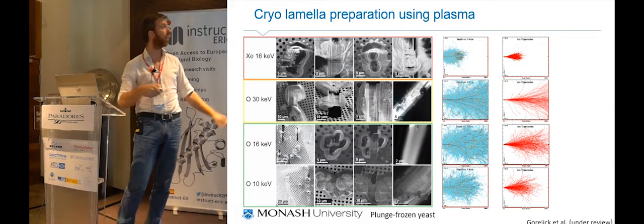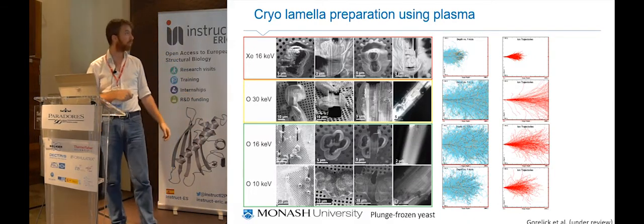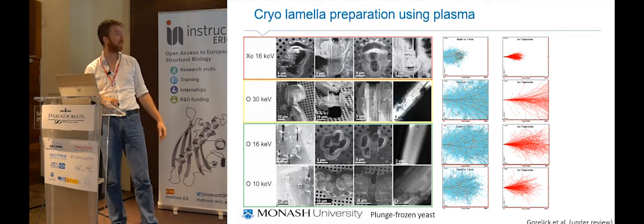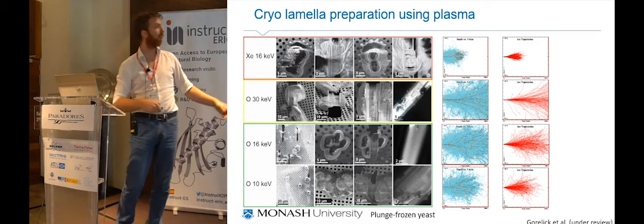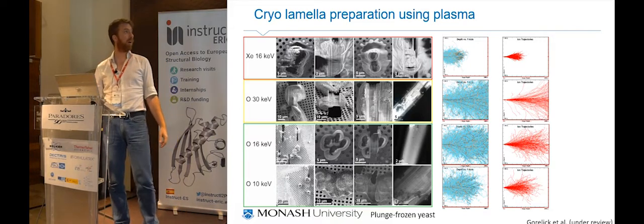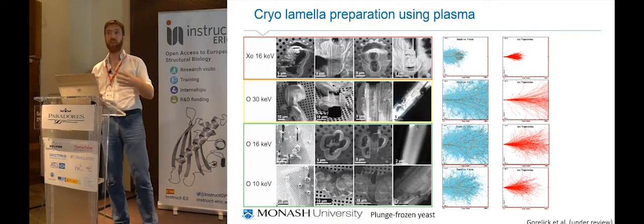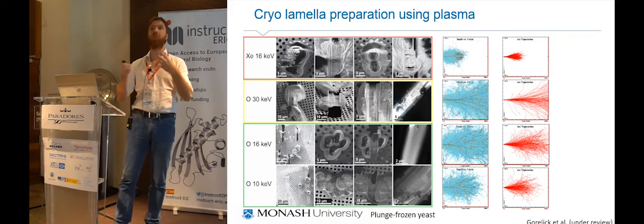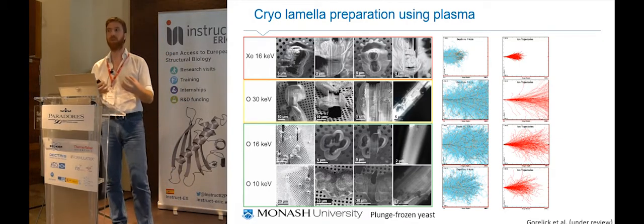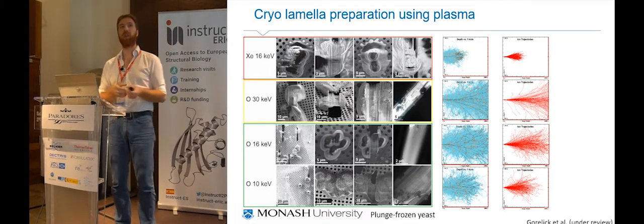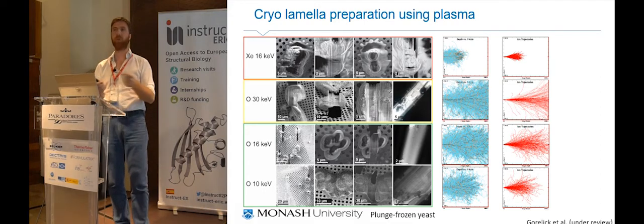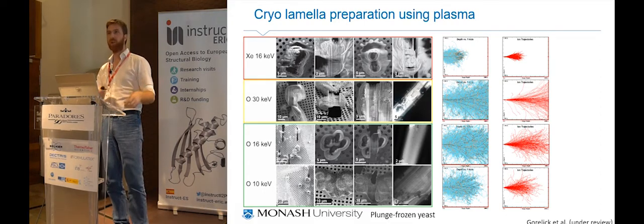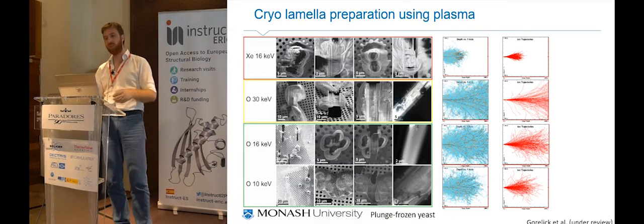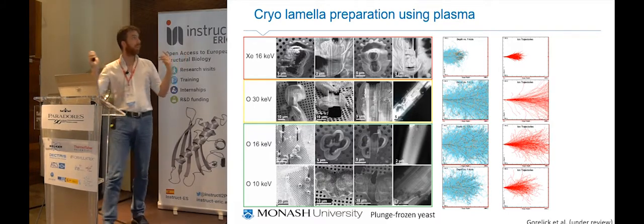30 kV, as expected, doesn't work. 16 kV and 10 kV start working. We actually get lamellas which are usable. The problem is that at 10 kV with oxygen we get almost no generation of secondary electrons, so we don't see our lamella when we cut it. We can cut a lamella in 7 minutes, super quick, and then we take an image with the SEM and there is no lamella. Then we do another one, super quick. Bam, there is a lamella. Yes, move to the next. Bam, no lamella, and so on and so on. Not very efficient.